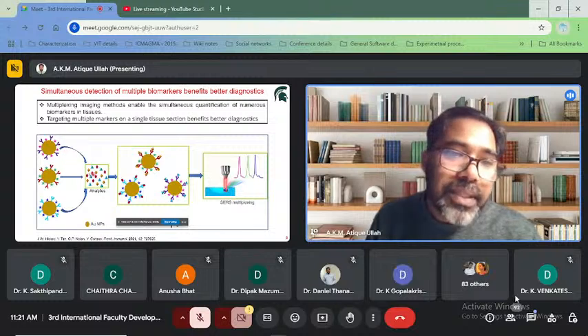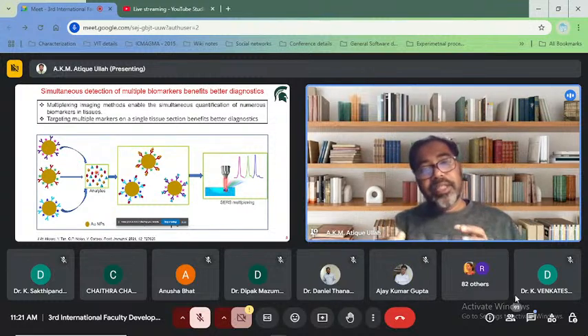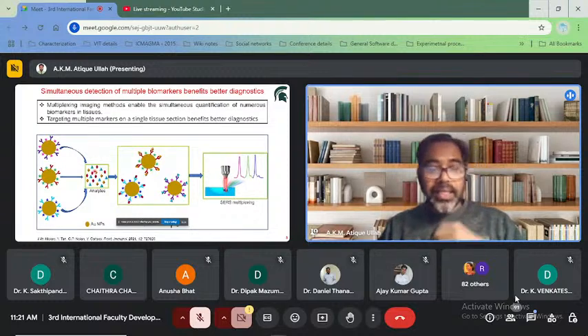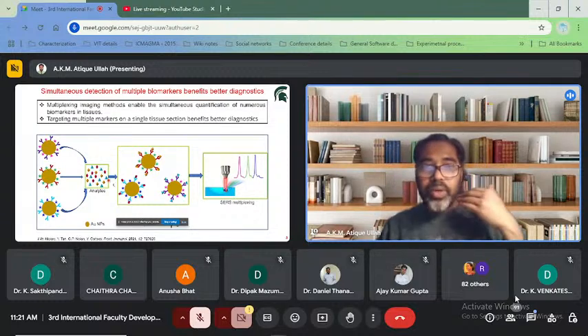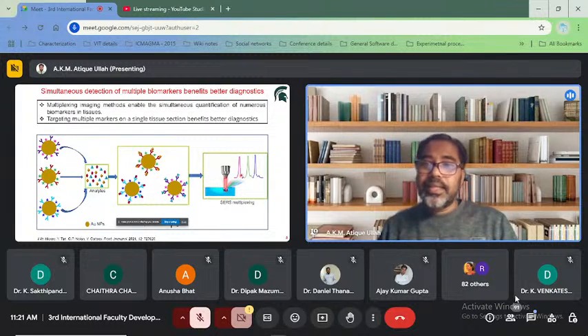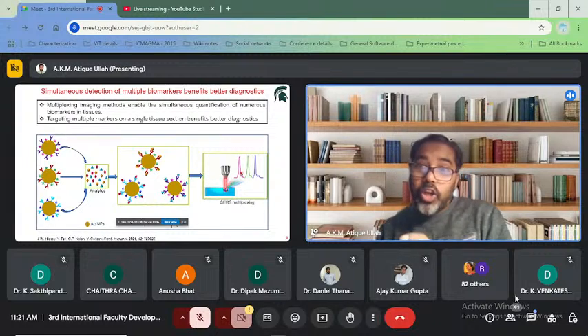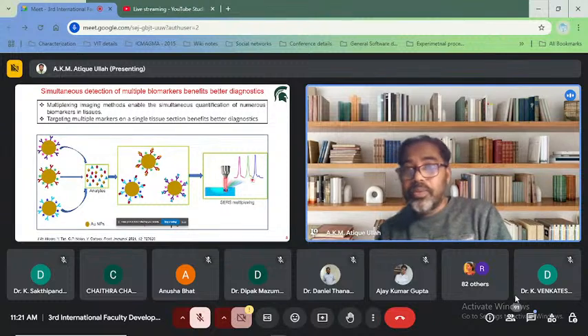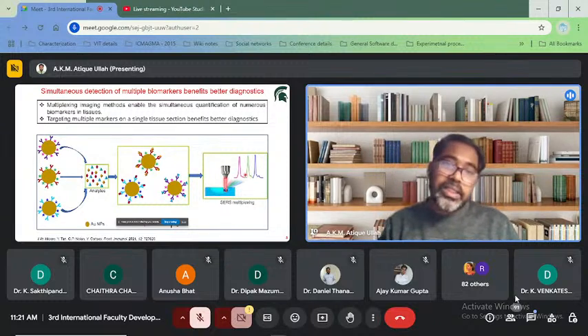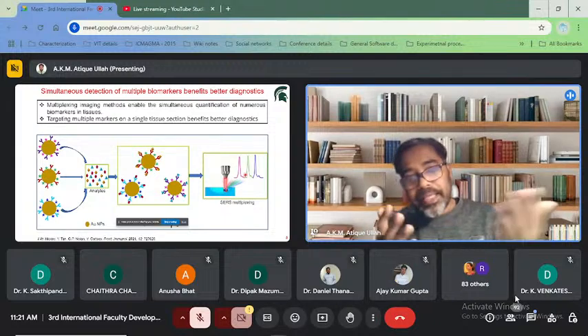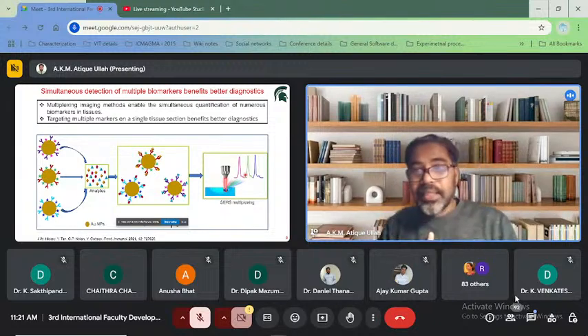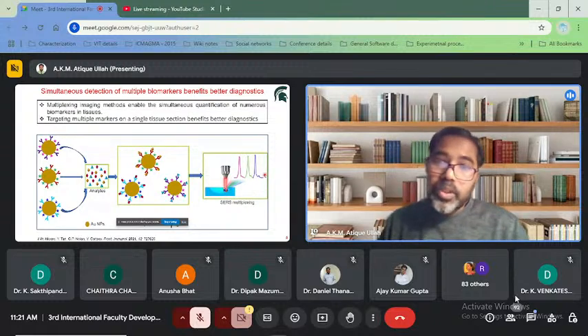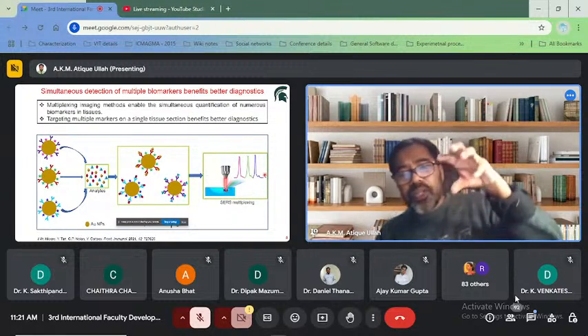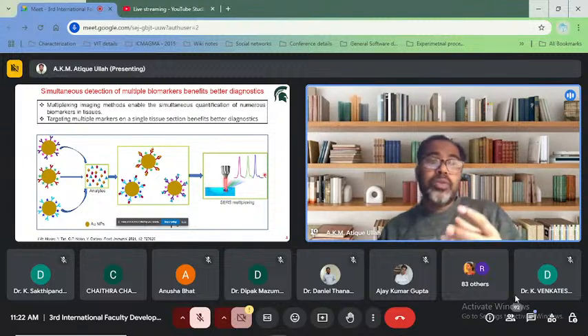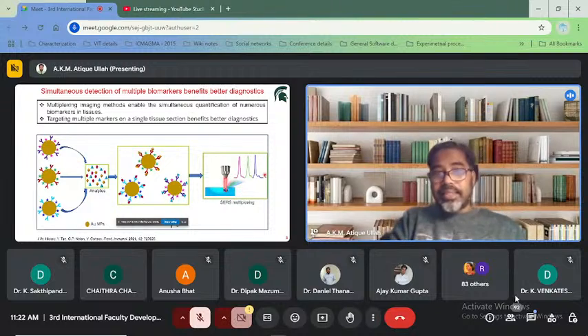Based on the receptor-ligand interaction, the SERS nanoparticles can bind with their respective analytes. Whenever we apply the laser, we get a signal from the Raman reporter molecule, so we can easily distinguish the analytes from the receptor-ligand interaction. And from the SERS intensity measurement, we can also quantify. So this is the general phenomenon of how SERS nanoparticles can detect multiple biomarkers in a single test.